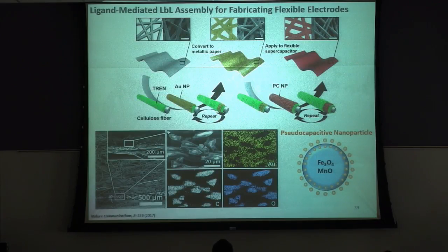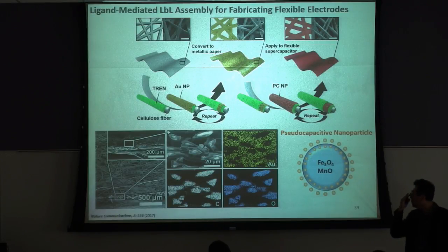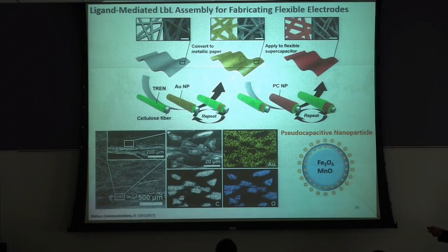So our goal is to design flexible and wearable energy storage devices, right? Generally people use paper or cotton or some kind of fabric as a substrate. But as you know, paper and fabric are insulating, right? So we first convert this insulating porous substrate to a conductive porous substrate. We convert this insulating paper to metallic paper by incorporating gold nanoparticles.